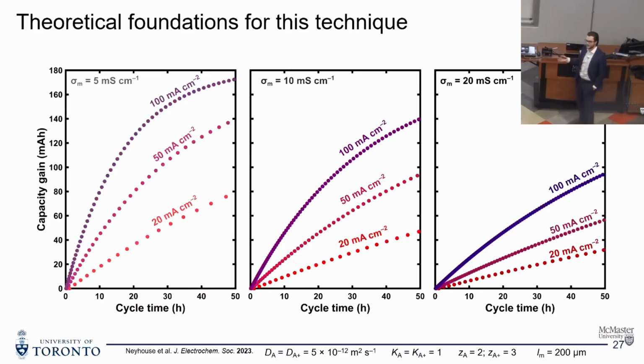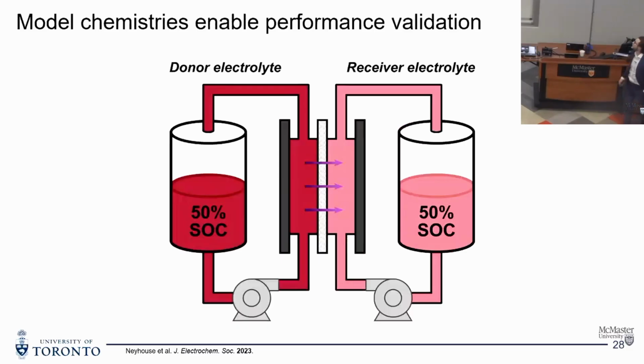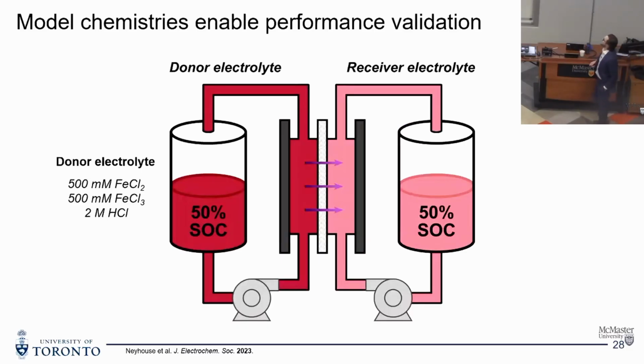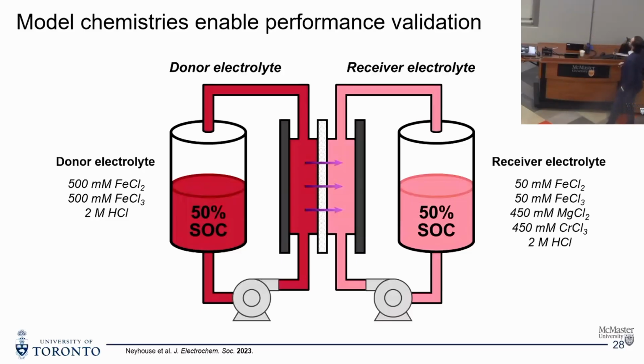So theoretically, we said this would work, but of course, we want to show that experimentally, right? So we use here a model chemistry. We use iron 2, iron 3. This is a really well-behaved redox species and has very well-defined transport properties. And this is in a hydrochloric acid electrolyte. Our receiver electrolyte is going to have a lower concentration of those species, along with some additional species to balance out the total osmotic pressure, as we can't have a total activity difference, otherwise we'd get osmosis.